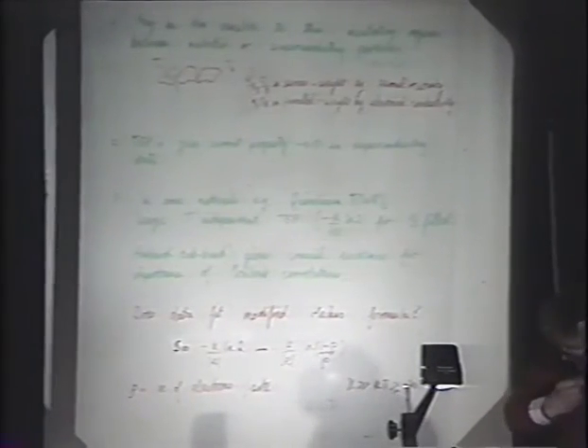I have a transparency here about the thermal power, but I think I shouldn't try to explain it at this time in 5 minutes. But one reason why the thermal power is particularly interesting is that in some materials, for example in organic conductors, a large temperature-independent thermal power, a famous minus 60 microvolts per degree K, which you can obtain theoretically for a half-filled Hubbard subband, gives crucial evidence for the importance of Coulomb correlations.